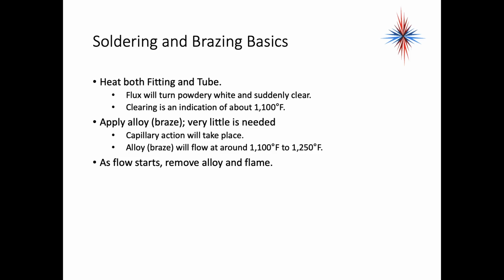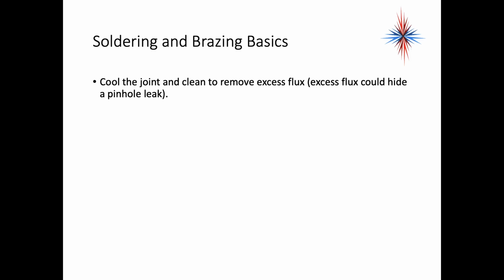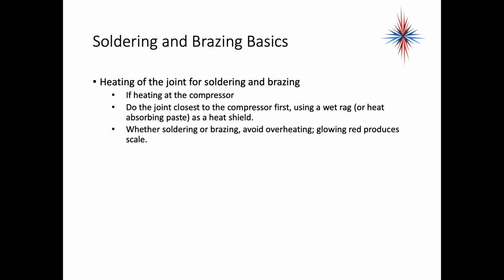As the flow starts, remove the braze and the flame. Cool the joint and clean to remove excess flux. Excess flux can hide a pinhole leak. Now, most often you're only going to use flux if you're brazing two dissimilar metals. When brazing copper, a lot of times you're not going to use any flux at all. It's not required. Heating of the joint for soldering, you've got to be very careful. If you're heating at the compressor, do the joint closest to the compressor first using a wet rag or heat absorbing paste as a heat shield. Whether soldering or brazing, avoid overheating. Glowing red can produce scale.